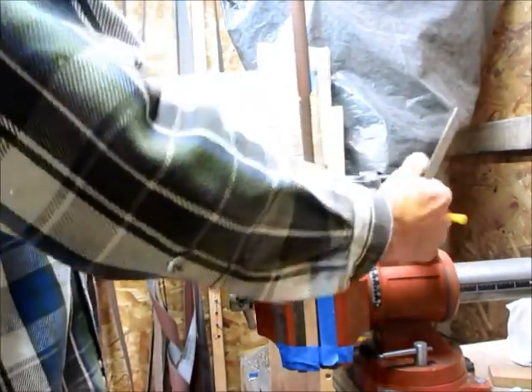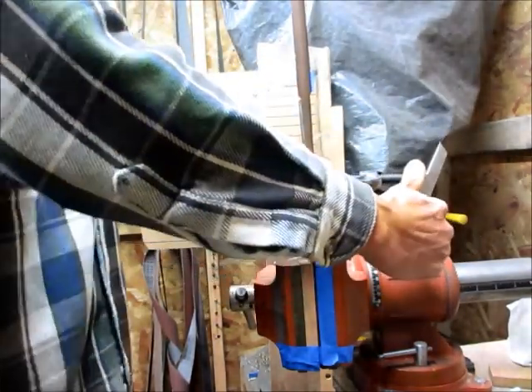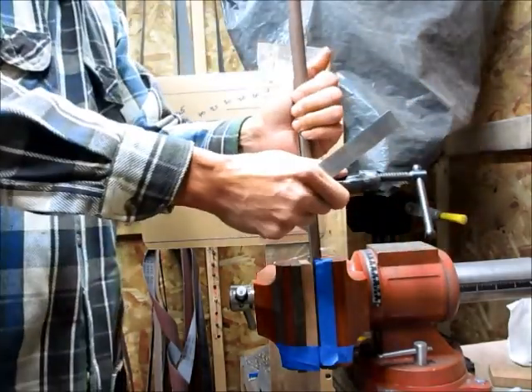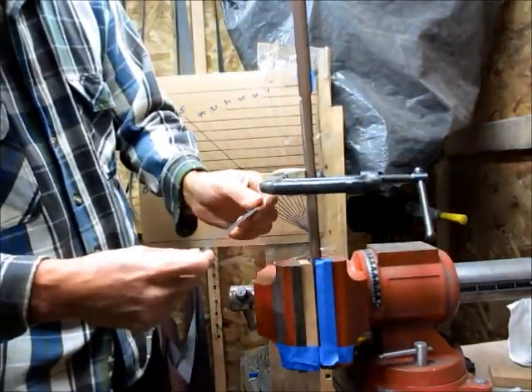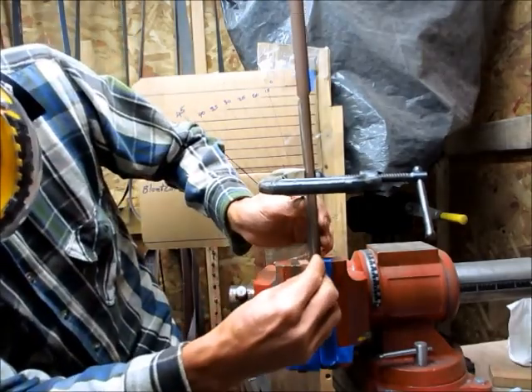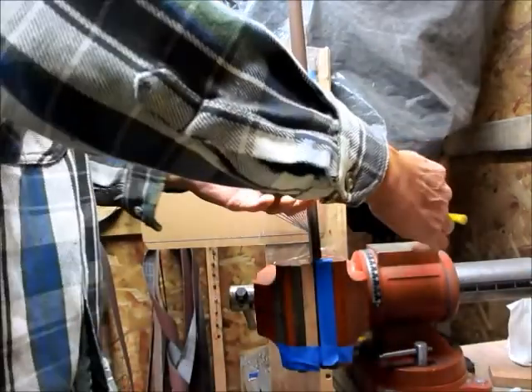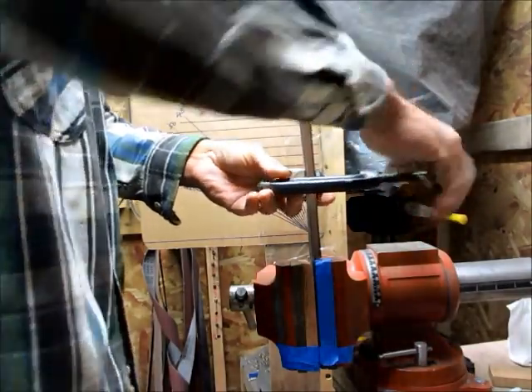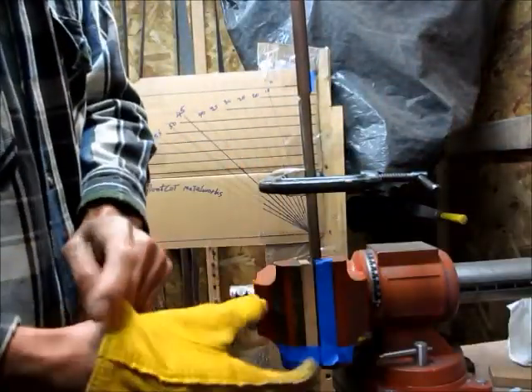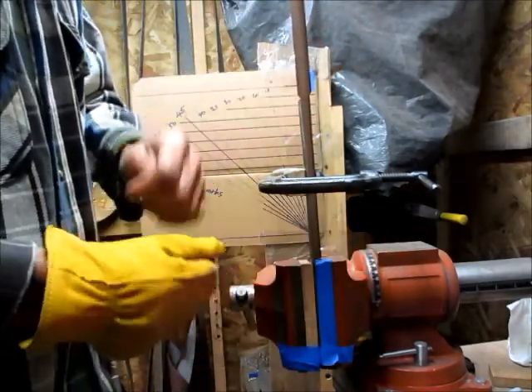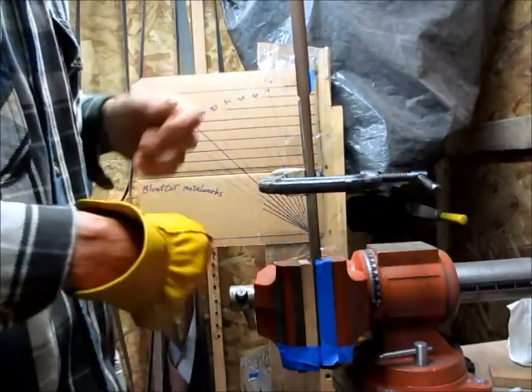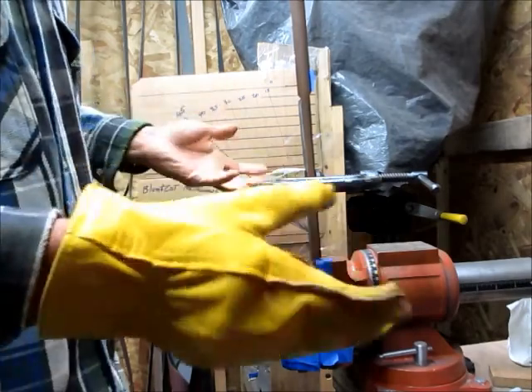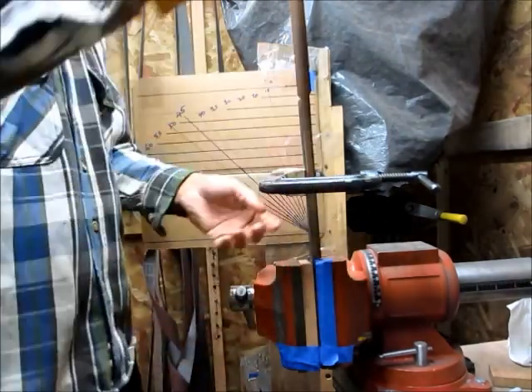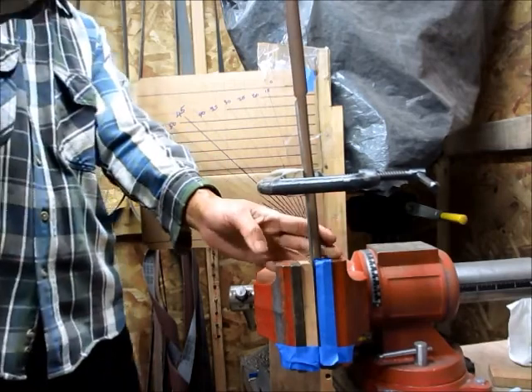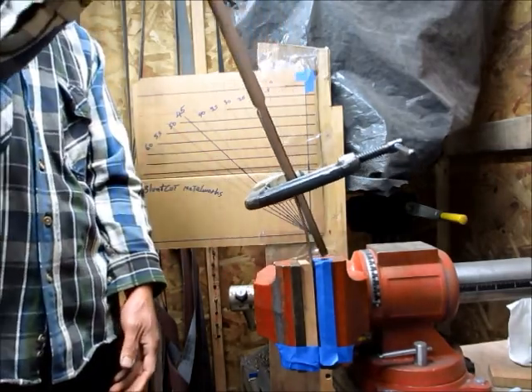In the process, either two things could be inconsistent: something in the bar, or in the temper process where the cementite precipitates. And sometimes in the process of precipitation, it may end up in the wrong place, like in the grain boundary or a different location. It could actually make the steel more brittle. They call it embrittlement. But this right here at 64 Rockwell,